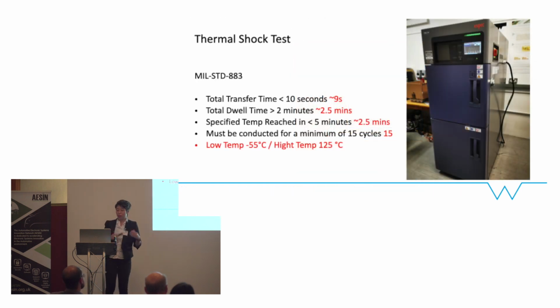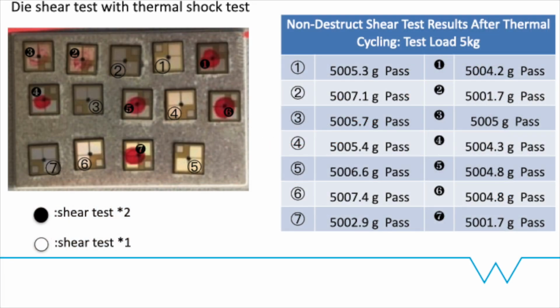And then is a thermal shock test. We use this thermal shock test chamber to test the mechanical reliability of the die attachment using the military standard 883. We set the high temperature chamber on the top at 125 degrees centigrade and the low temperature chamber at the bottom at minus 55 degrees centigrade. And the test specimens are kept still in one chamber for 2.5 minutes and rapidly moved to another one within 10 seconds. And this cycle is repeated 15 times. And after that, this is our result.